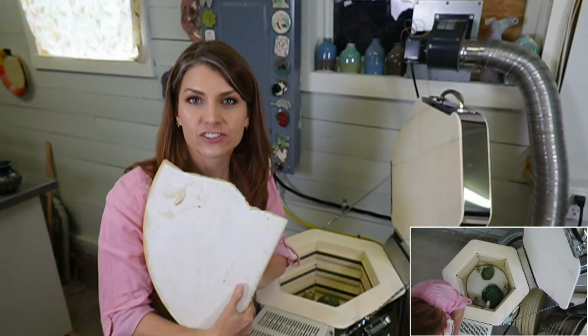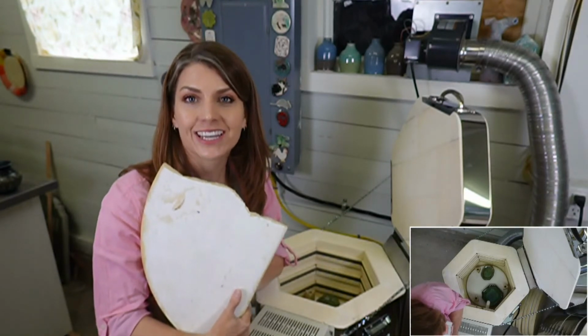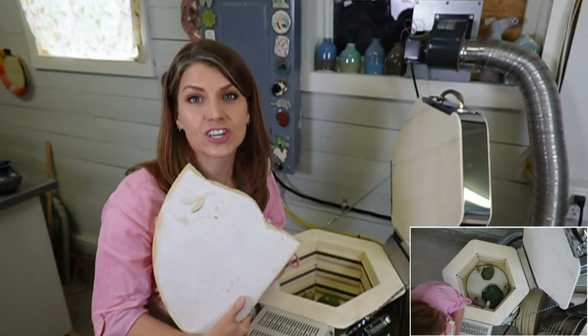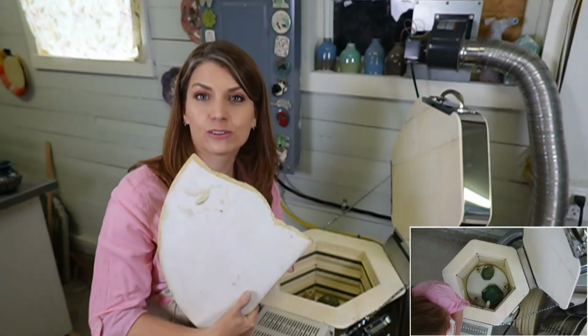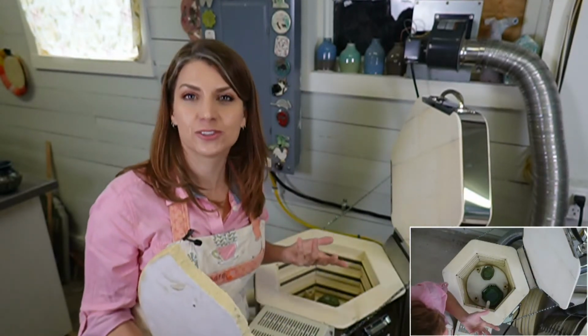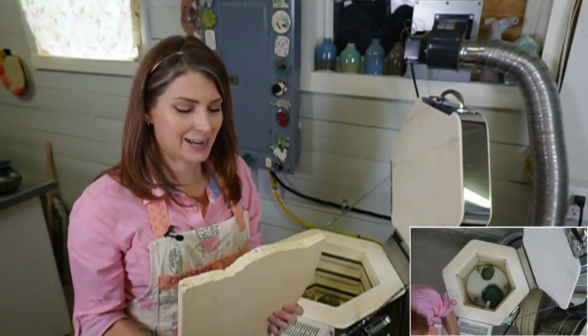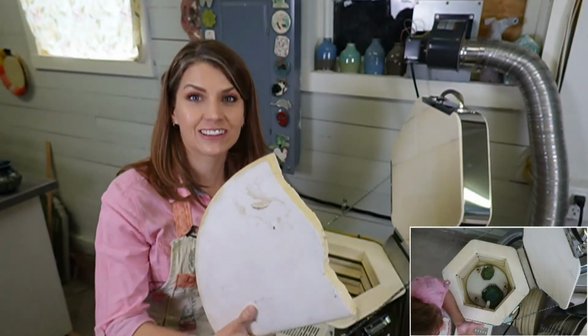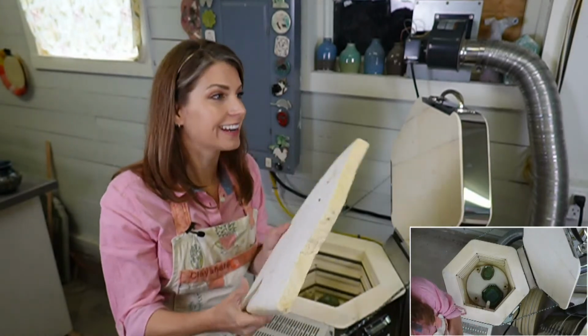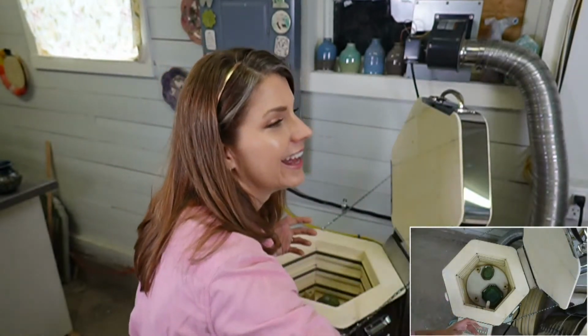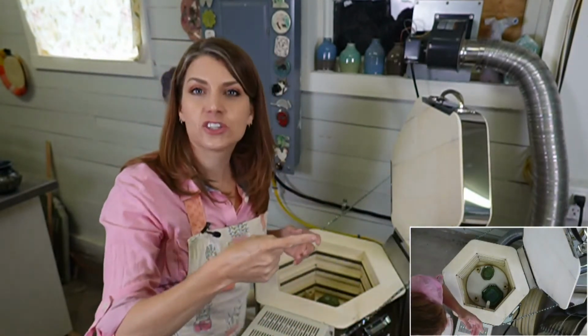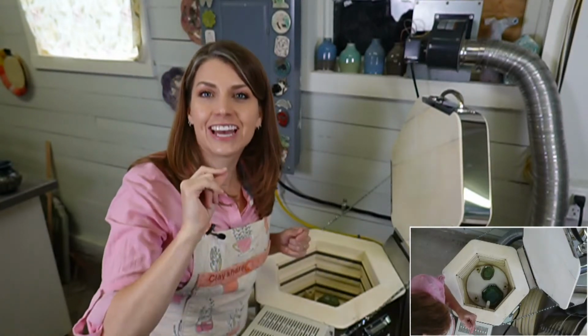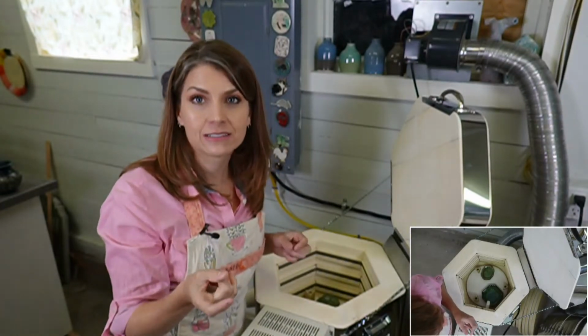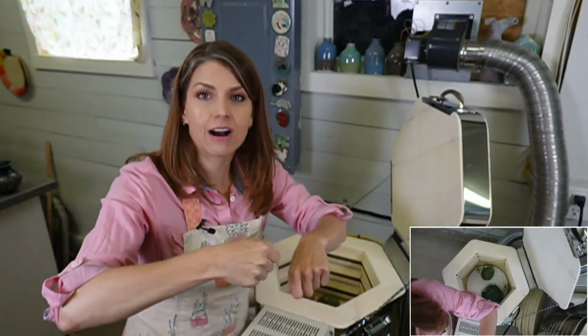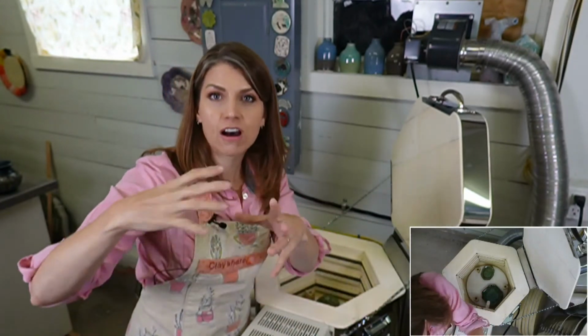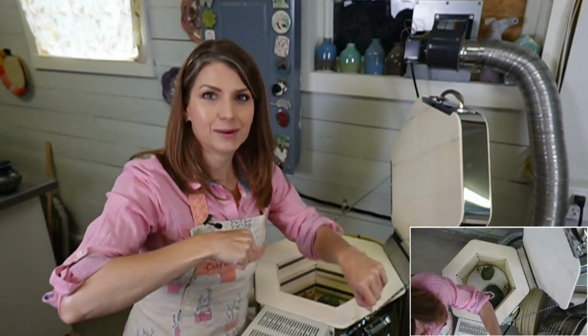But I would not suggest this for a professional result. I would use a tile saw and make sure it's very wet and cut it with a tile saw. That's what I would suggest doing now. But me in my studio, sometimes, that's the whole thing. Do as I say, not as I do sometimes. I knew better, but I didn't have a tile saw, and I needed half a shelf. Kevin says you might be able to get away with an angle grinder and a masonry blade, but you've got to keep it wet when you're doing it. Make sure you have a bottle of water you're pouring on this shelf, not the whole saw, not the electric part, just the shelf part. Please?